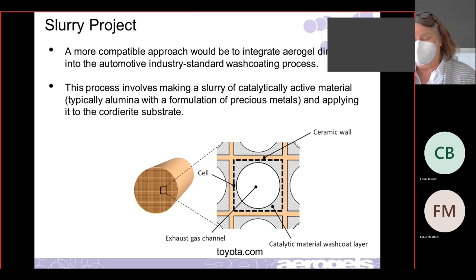What they do is they take the big cordierite monolith, that big piece, the structure, and they dip coat it in a slurry that has alumina and the platinum group metals. They probably do multiple processes: dip it, then dip it in something else, then heat treat it. But the basis of the method is to make a slurry of the material, which means you have to get it wet. So we made a slurry of aerogel and a little bit of pH 4 water. We had to mix them together.